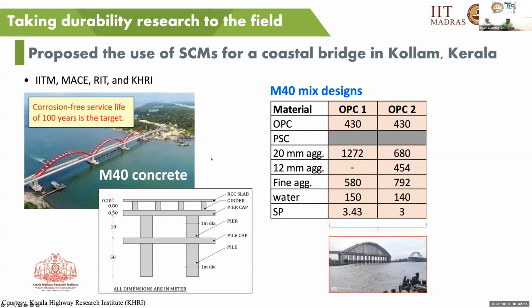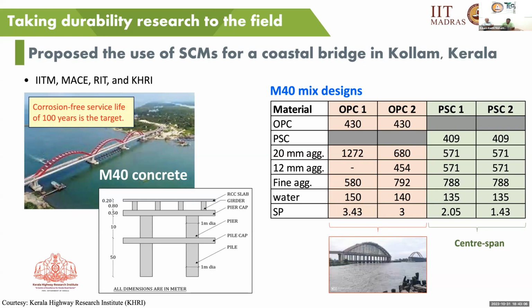And they were actually using M40 mix designs, as you see, with OPC-type concrete. What we suggested to them is to go for slag or any other SCMs possible, but we eventually decided to go for slag-based concrete because it's a coastal region. If you look at the photograph at the bottom, the mid-span, by the time we were able to influence, the project was already up to this stage, but luckily we were able to use the slag concrete in the mid-span.